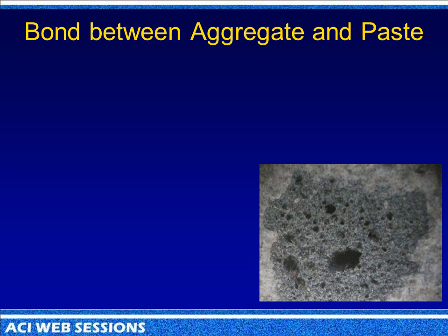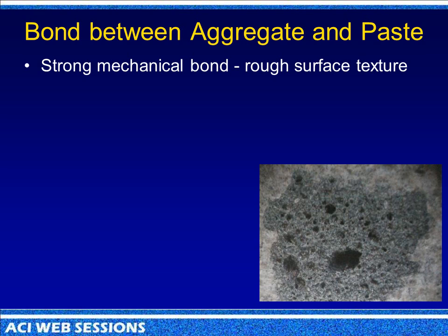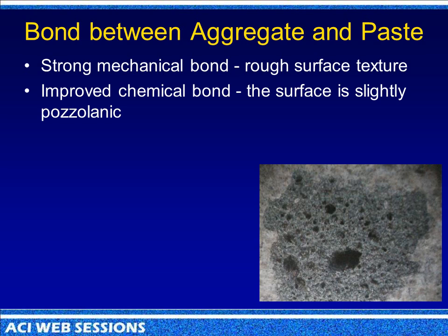Now, also we improved the bond of the aggregate. So this is a lightweight aggregate. You see, look at the rough surface texture on this thing. Look at the voids inside the aggregate. And there's a strong mechanical bond because of that rough microsurface texture. And there's also an improved chemical bond. And that chemical bond, because the surfaces of these aggregates are slightly pozzolanic. And that reduces the microstructure, the microcracking.